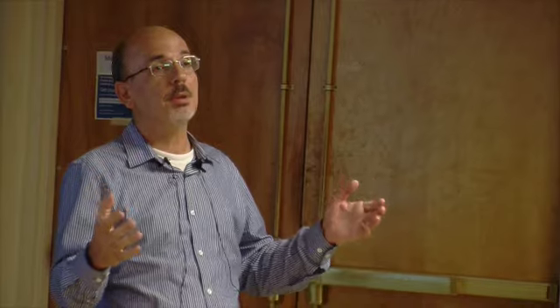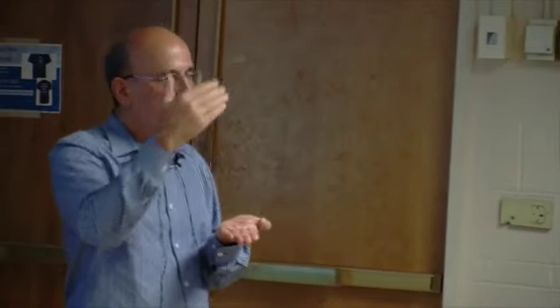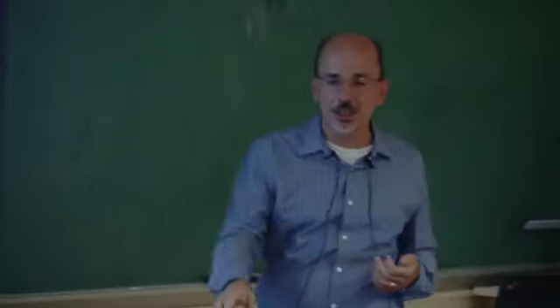And you can play around, and that enhancement, instead of 3, can become, like the previous slide, can become 20. Some people talk about 100 times enhancement. So as you increase the thickness of the silicon, you reduce Forster energy transfer, but keep some of the field enhancement, and that's the reason for emission enhancement. So you go from suppression of emission to enhancement of emission, and this is the lifetime of those.